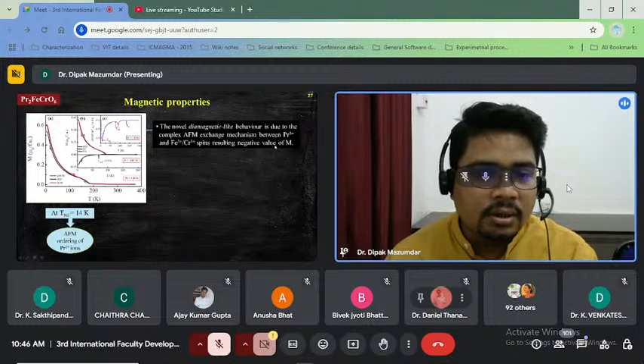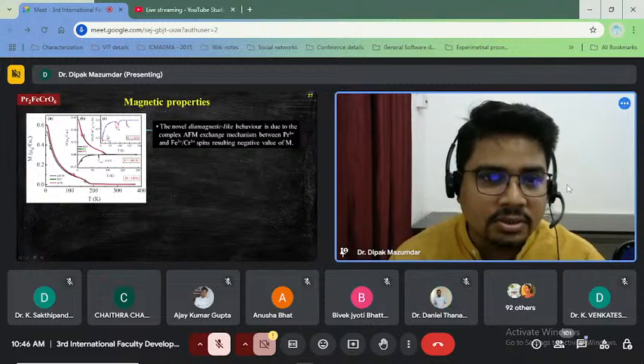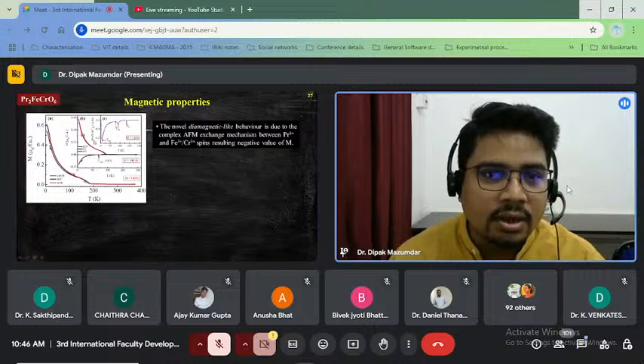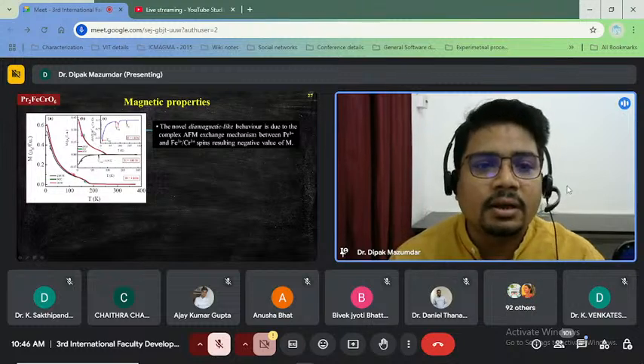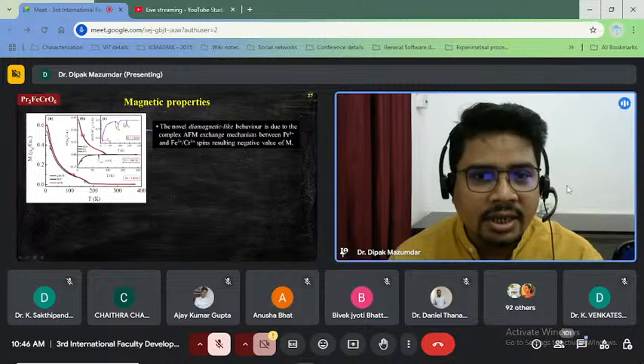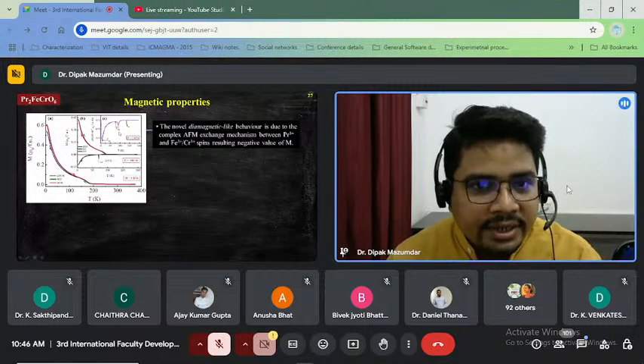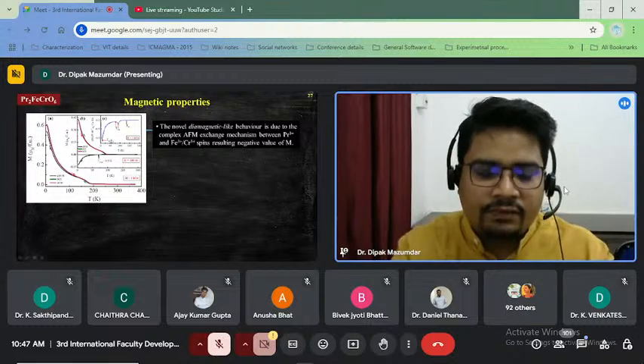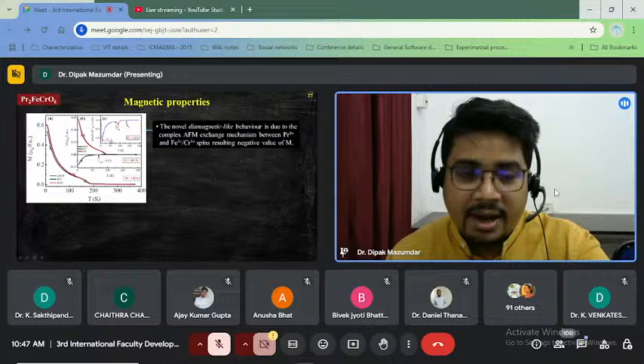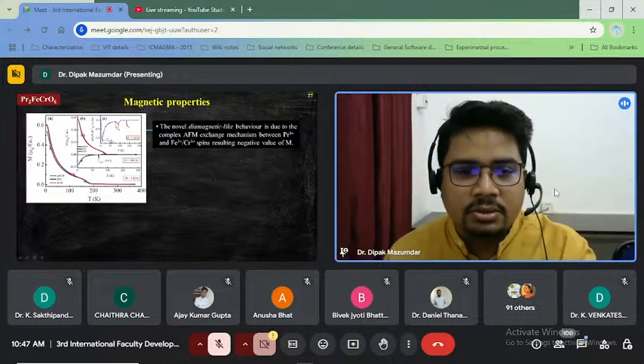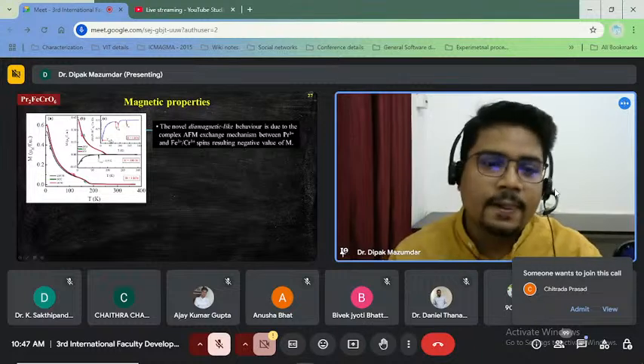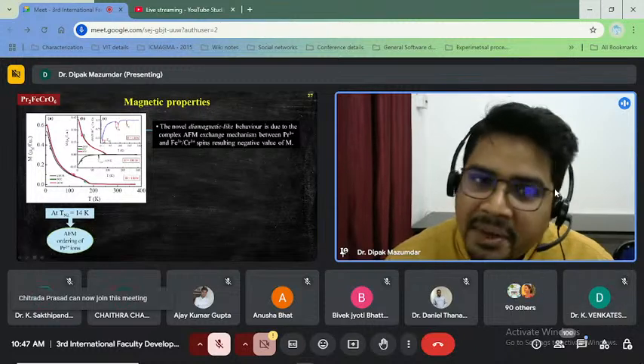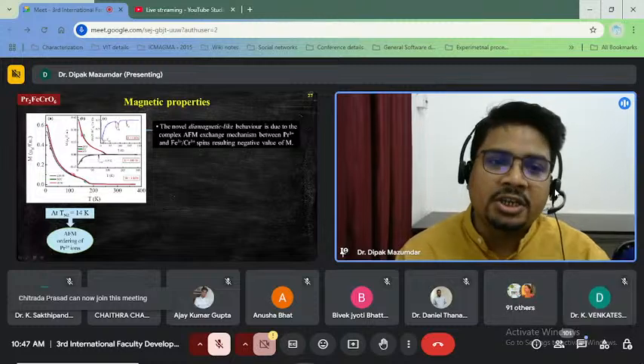Next, I will check these transitions using the first derivative of this magnetization curve, which is known as the dM/dT curve. And from this data, I have seen three transition points, and I already mentioned the magnetic table of double perovskite compounds. So here we will try to relate those magnetic tables with these transitions. The first transition I am considering here is at TN2, around 14 Kelvin, and this is the low temperature ordering of praseodymium ions, where iron and chromium do not play any role.